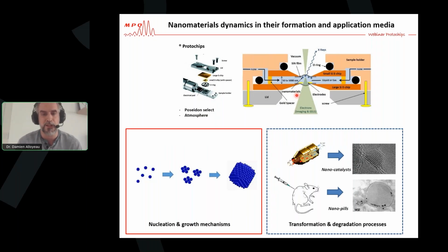So a brief reminder of how those sample holders work, the Poseidon, Select, and Atmosphere systems. The idea is to encapsulate the liquid and gaseous environment with those silicon nitride chips. So these chips are a silicon wafer on which you have a window that is covered with silicon nitride films that allow you to seal the liquid or gaseous environment, and you can control the composition of the environment by injecting any type of liquid or gas at the observation windows.